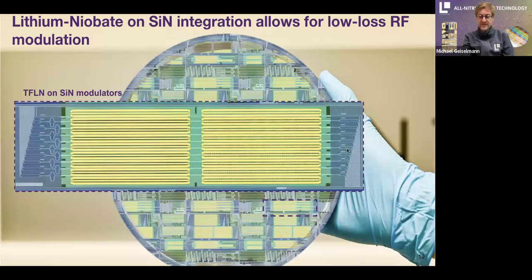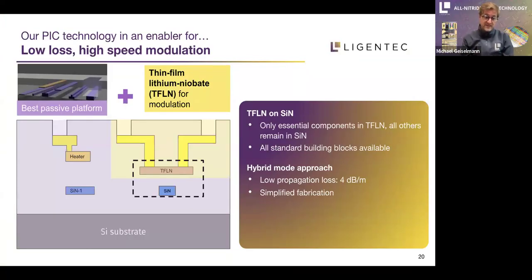Mach-Zehnder interferometers with lithium niobate. And then we go down again into the nitride and back to the passive components with extremely good edge coupling of the chip. So we combine the best passive platform that we have demonstrated we can fabricate in volume, which has nitride and heater integration, and put the thin film lithium niobate for modulation only where needed. So this only takes the essential components for lithium niobate.